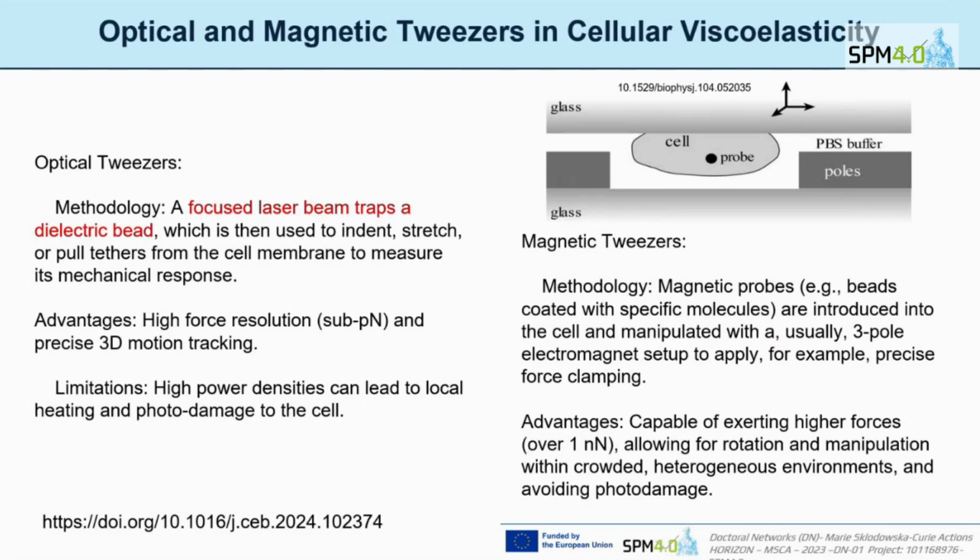We put inside, for example, inside the cell, either a microsphere with different refractive index or some magnetic particle, and we observe by changing the fields the movement of the particle inside the cell, and from that we can obtain information about viscoelastic properties, because usually we move the particles, making them oscillate. So this is some kind of oscillation rheological measurement.